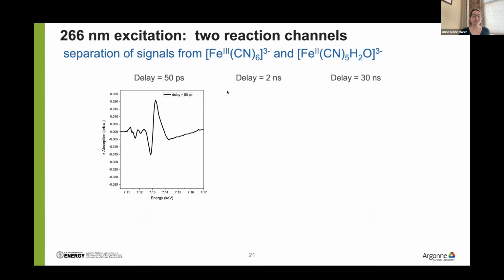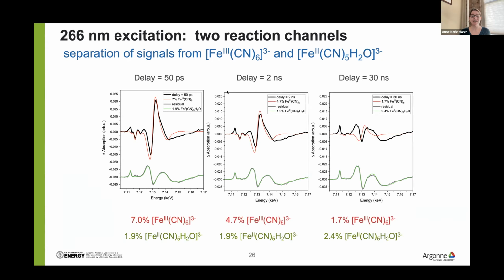Here's our measured difference signal. Here's the ferricyanide component. Here's the subtraction of the measured signal minus the ferricyanide component, what I call the residual. And then in green is the difference spectrum that we measured for the aquated product. You can see it matches very well. From this, we can say that at 50 picoseconds, we have 7% ferricyanide and about 2% aquated product. We can do the same for the other 2 delays. You can see that the amount of ferricyanide decreases with time, and the amount of aquated stays constant, except that at longer delay, it seems like it's increasing a bit.